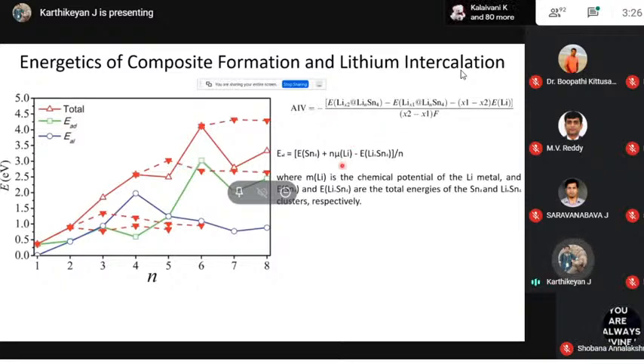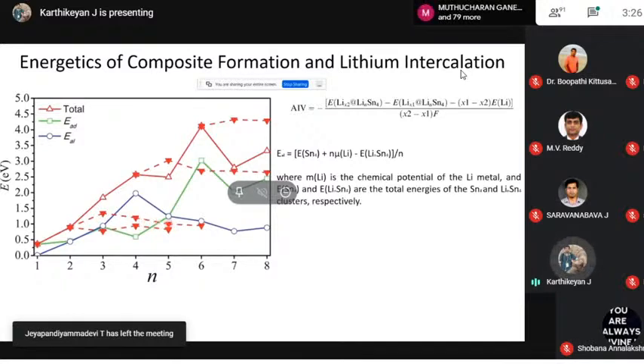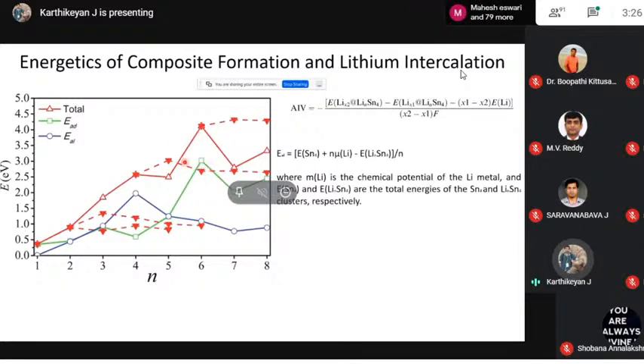Then we calculated the intercalation voltage for every step. The dotted lines are the intercalation voltage calculated for every step. So here again you can see that the intercalation is not a dominating process. Intercalation becomes a dominating process when you reach N equal to more than 6. That means first the alloying happens, then the composites are getting more and more stable. Once composites are completely formed, then the lithium goes to the pores of the CNT walls.